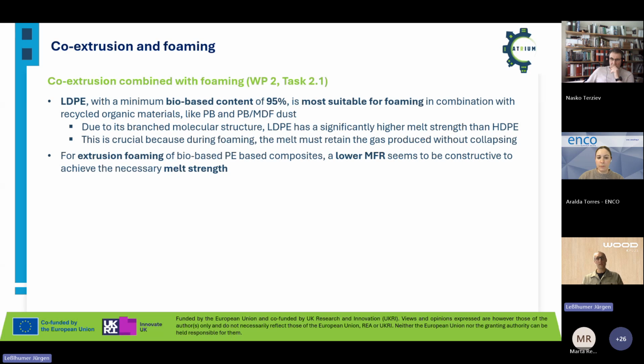And some words about the materials we used. We have evaluated that LDPE is the most suitable for foaming, for one main reason. Its branched molecular structure has a significantly higher melt strength than high density polyethylene, and high melt strength is crucial during foaming because the melt must retain the gas produced from the decomposition of these chemical foaming agents without collapsing. And we saw that for extrusion foaming of bio-based PE-based composites, a lower MFR seems to be constructive to achieve the necessary melt strength.